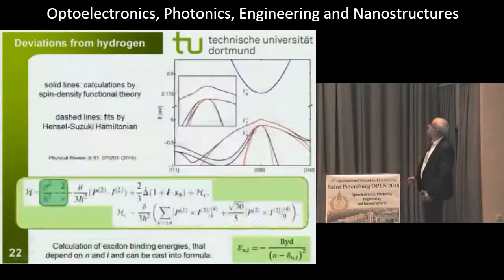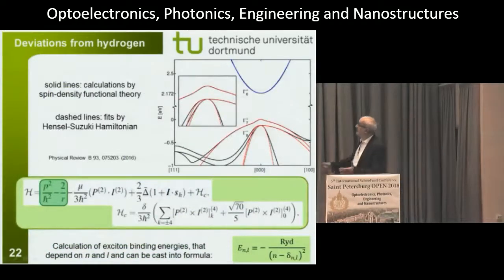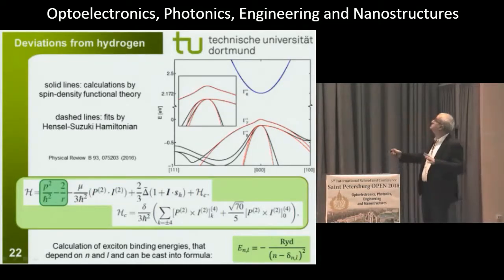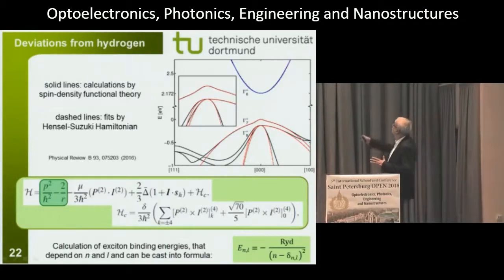You can model this also. I just want to point out the details of this modeling. This is the Hamiltonian that we use. It's already a very much simplified Hamiltonian. We also did full spin density functional theory calculations. These are the black lines here, but for really calculating the exciton problem, we use fits to these black lines, shown by the blue and by the red lines here.